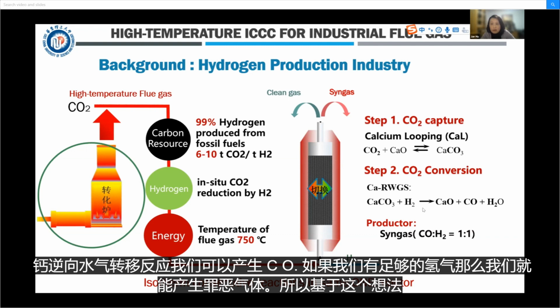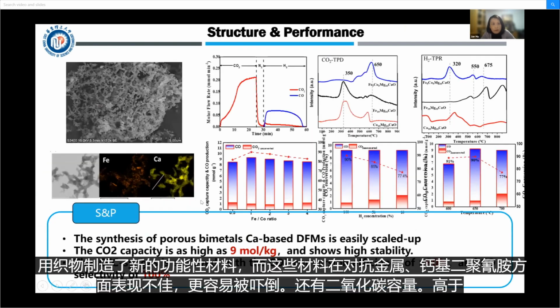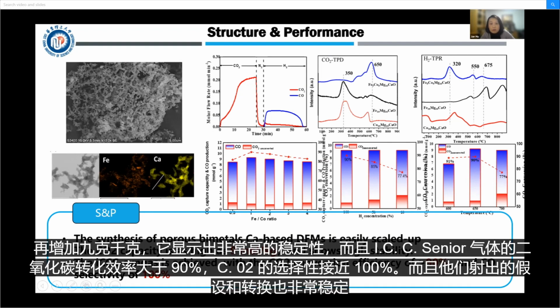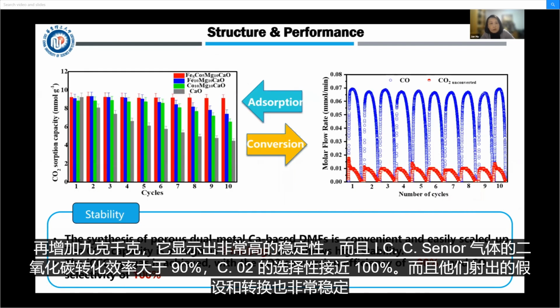We can produce CO, and if we have enough hydrogen, then we can produce the syngas. Based on this idea, we fabricated the dual functional materials. These are porous metals, calcium-based DFMs, which are very easy to scale up, and the CO2 capacity is as high as 9 mole per kilogram, and shows very high stability. The ICCC syngas is achieved with a CO2 conversion efficiency of larger than 90% and a CO selectivity of almost 100%.